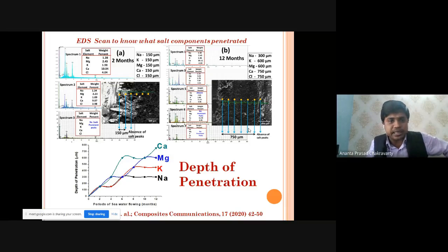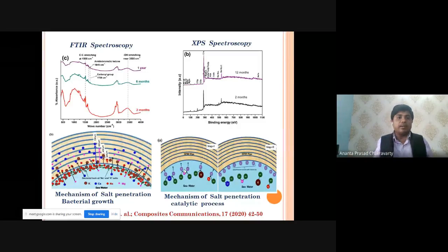So hence I have gone for elemental mapping of the surface of the pipes. I can see the salts: calcium, magnesium, potassium and sodium, with calcium penetrating more and sodium penetrating very little. And I have gone for Fourier transform infrared spectroscopy. At 1 year, I can see some additional groups, such as amide, aromatic ketones and carbonyl groups, forming due to some additional polymeric or organic functional compounds, and those are packing inside it and giving strength to the materials. Similarly, by XPS analysis, I can see how much salt is associated with the surface. So hence I have studied the mechanisms by